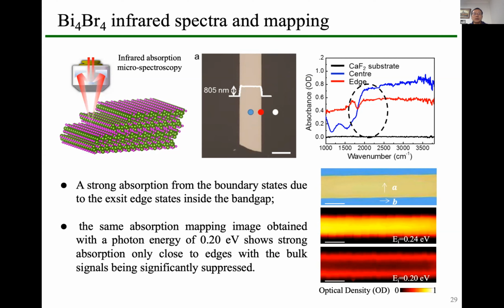The main result is this: if we illuminate this material with high energy photons, we find that the light absorption is essentially from the bulk. You can see that the center of this nanowire has a very strong absorption of this energy of light. But if we use low energy photons, we find that the light absorption is essentially localized at the boundary. This means that the boundary, or the edge, of the nanowire can effectively absorb low energy photons. This is consistent with our physical understanding of this material, because the edge state can absorb low energy photons.